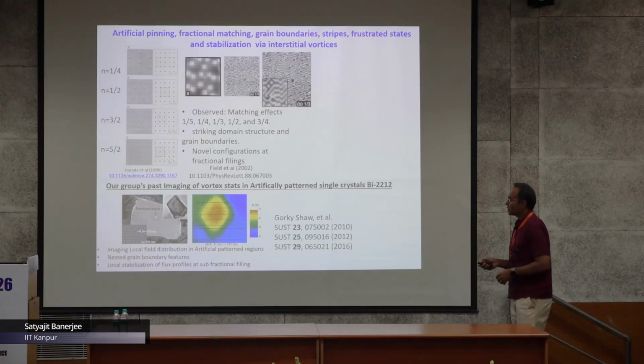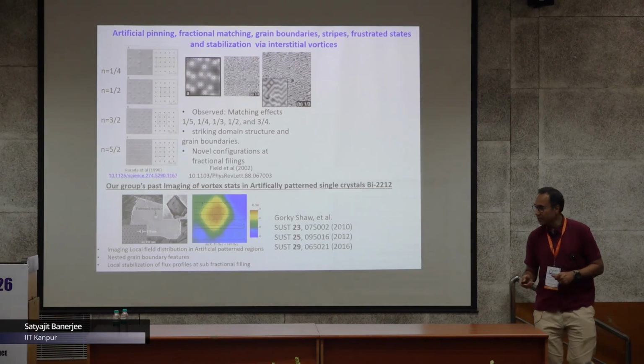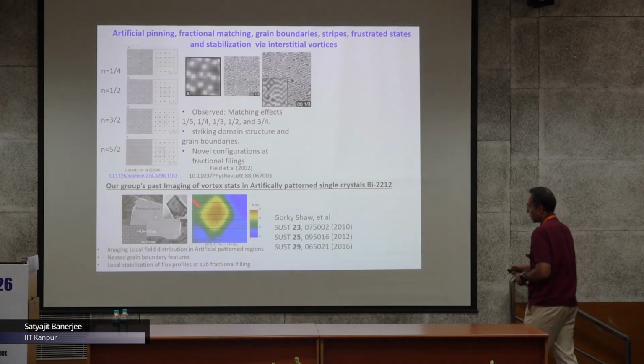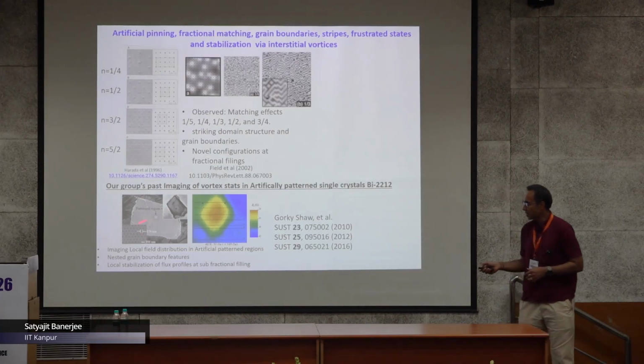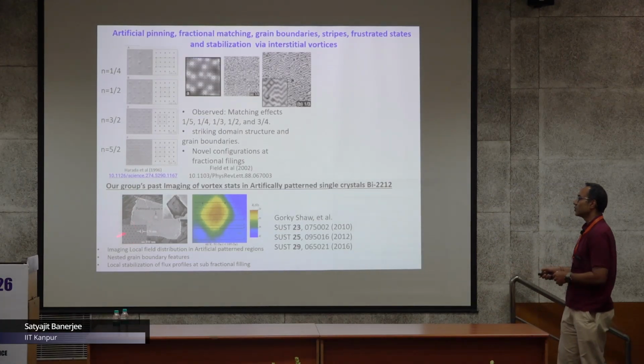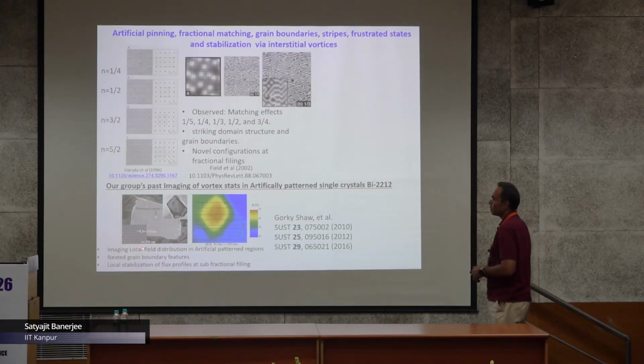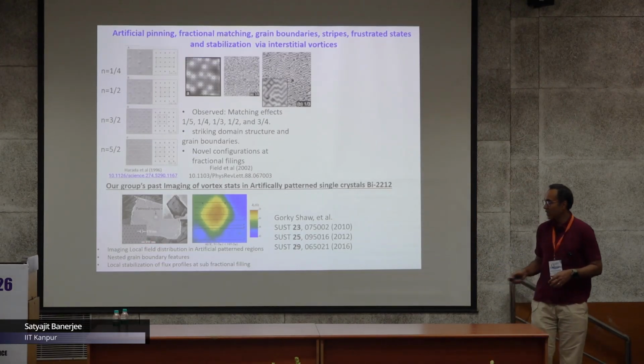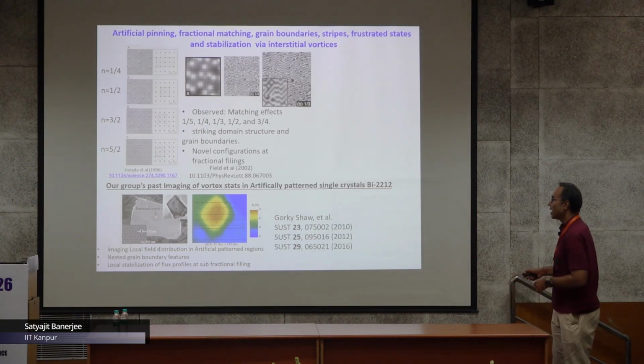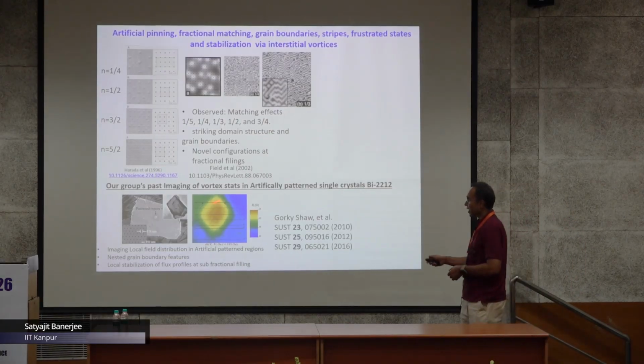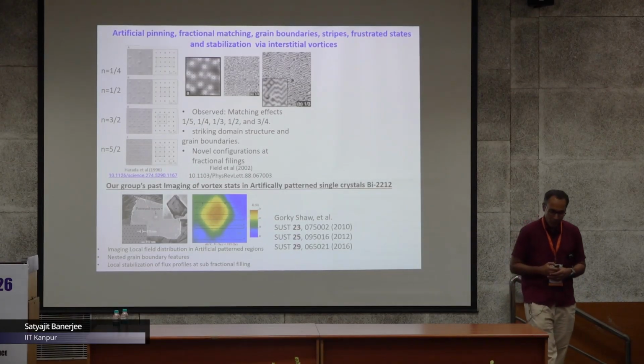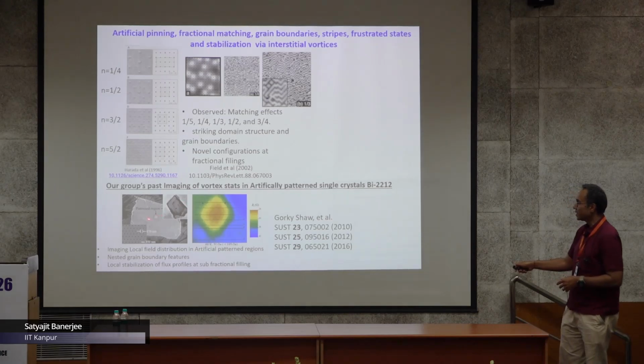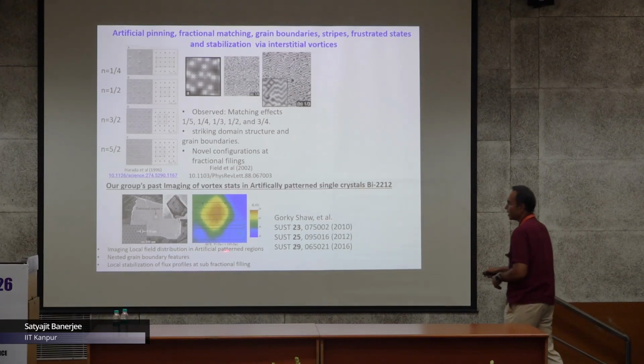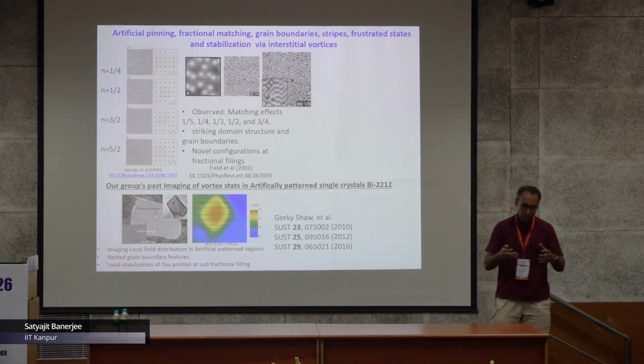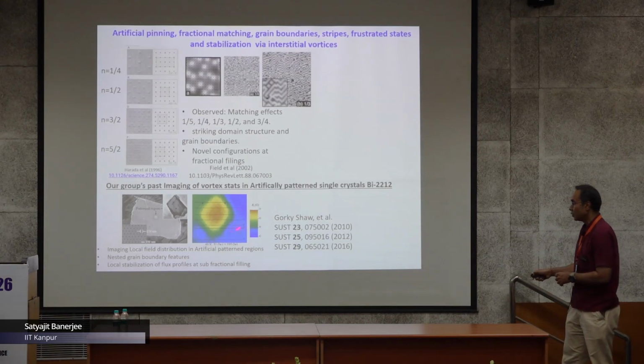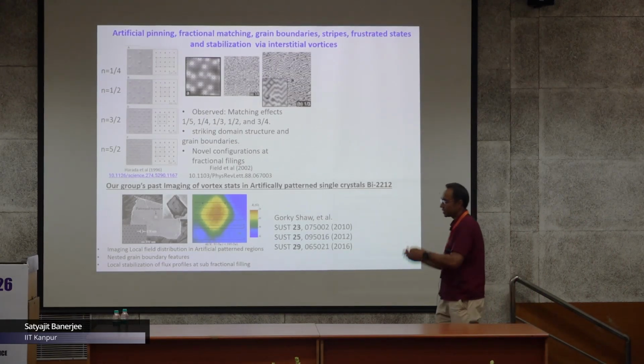This has been there for some time. Our group, way in the past, has actually also done work on these patterned structures where, for example, in BSCCO with a focused ion beam, we patterned this periodic array of 350 nanometer sized holes, and we could control the flux, the fractional filling, and we did imaging on the vortex configuration inside these patterned regions where there is fractional filling.